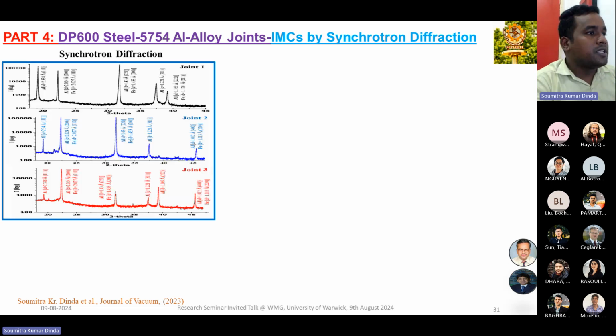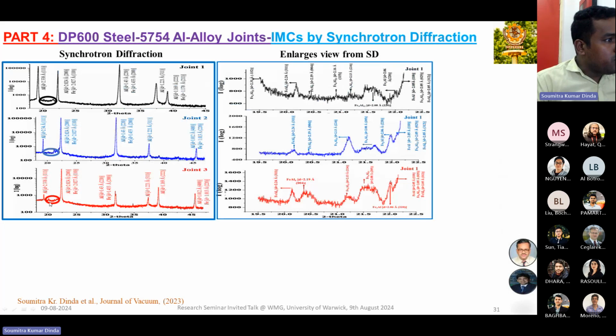For that, we did a synchrotron diffraction study. In normal XRD the wavelength is 1.54 angstrom, but in synchrotron diffraction the wavelength is 0.7843 angstrom. And this is the synchrotron graph. Here we only saw the iron and aluminum peaks, but in a small portion you see some small peaks. Then we scanned the sample in the small 2 theta region, from 19.5 to 22.5,